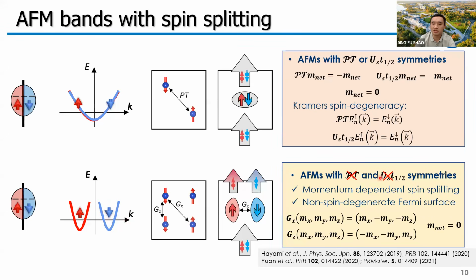And even without these two symmetry operations, we can still have zero net magnetization with the help of some crystal symmetries. For example, here I show a glide mirror symmetry Gx and a glide Gz. Gx can preserve the x component of net moments, but flips My and Mz. And Gz will preserve Mz, but flip Mx and My. So if we combine these two symmetry operations, we will get zero net magnetization.